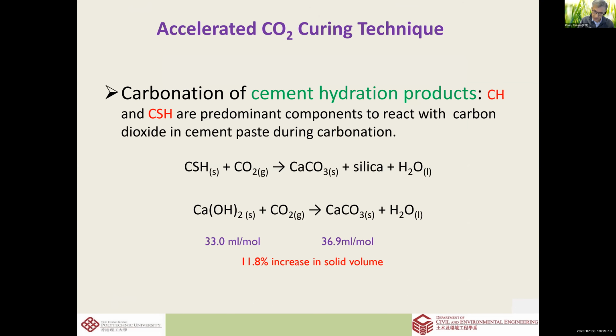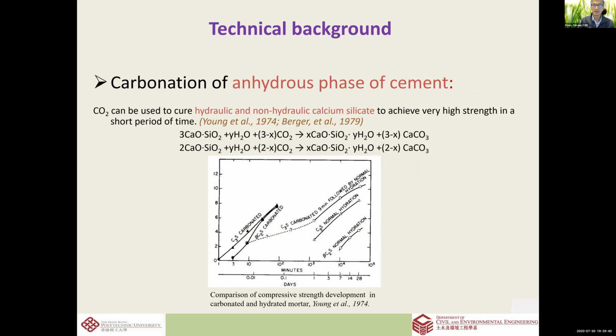So this is the principle. The hydrated cement contains calcium hydroxide, particularly. When it turns to calcite, it has some volume increase. This volume increase leads to densification, as well as the mineral change from portlandite to calcite leading to hardening as well. Okay, so this is not new. I think this was done 30, 40 years ago by